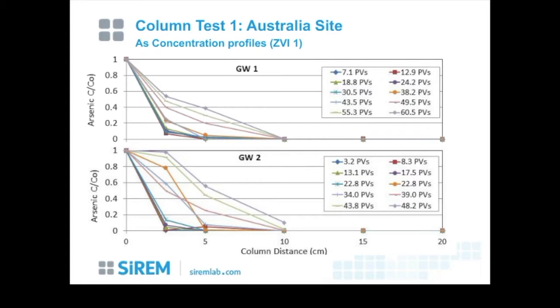And you can see in groundwater 2, we had much better treatment at this first port, and that, however, we did see breakthrough over time. Essentially, in groundwater 2, we had better removal, but no reactivity with time, and we had a lot less pore volumes in groundwater 2. So we had some different results from each one of them, and they were very useful to the ultimate design of what they were going to use in the field.